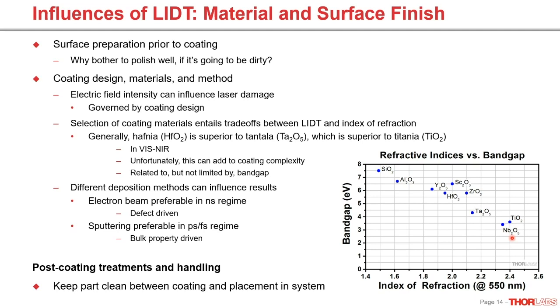So this leads to almost a rock, paper, scissors type of game when it comes to designing the coating, because you want something that has a high damage threshold, but you also want something that's less complex, and less complex equals fewer layers. So yes, there are trade-offs to be made there. Damage threshold isn't necessarily defined by band gap, but that's a good proxy to look at.